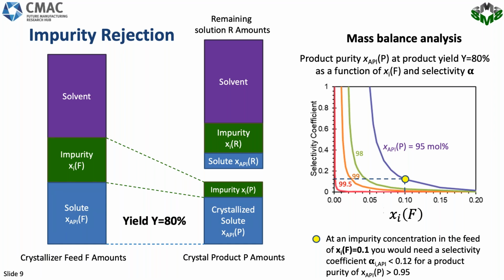Another question related to the conglomerate co-crystal solvates. How can you ensure the solvate is of conglomerate and not a racemate? Yeah, it is described in the article how you can get indications, and then to be sure is to make a single crystal and determine the structure. So if you find in the structure only one of the enantiomers, then you can be sure that your system is a conglomerate system. How do you choose the amount of BPE to form a conglomerate co-crystal system?